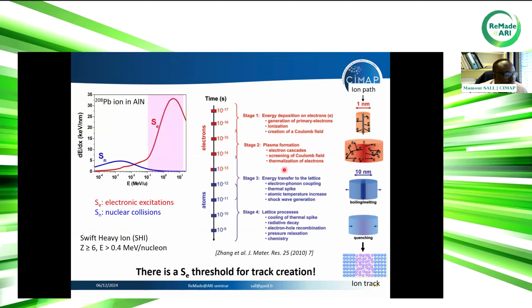Okay, what I did not say is that the swift heavy ion creates tracks by the mechanism I showed at the beginning. So we have the ion exciting delta electrons and transfer of the energy to the lattice by melting. But this happens only if the energy transferred by the ion is higher than the energy required to melt the material. So by playing on the electronic stopping power, the value of Se here, we can be below the energy needed for the material to melt.